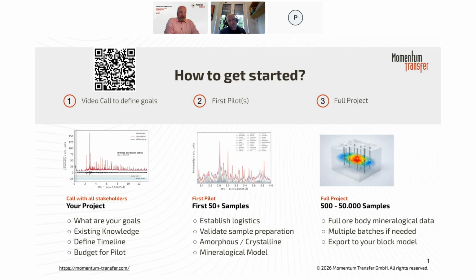And the other thing is, you could take other materials and calibrate them against the NIST standards. The NIST standards do have values for the amount of amorphous content, which can come from surface relaxation on the crystallites, regardless of size, but also from defects that are inevitably present in the material. So you can mix one of those NIST standards with your new material to calibrate the amount of amorphous content in it, and then you can use that other material as a calibration standard as well. So those are pretty much the main things to keep in mind.